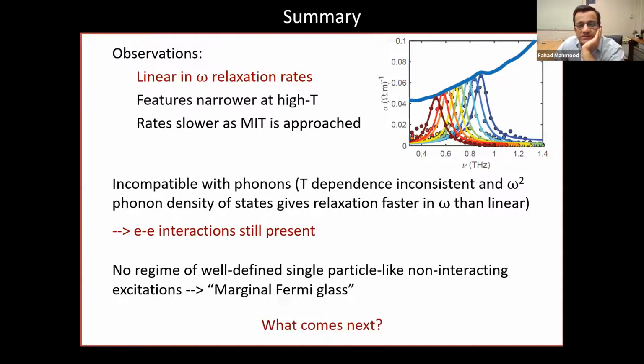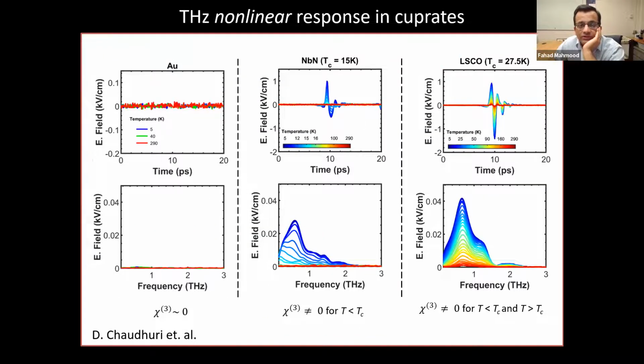As a follow-up to this, the student that I was working with, Dipanjan, has been working very hard to extend this to cuprate superconductors, and I thought I should flash these results because this is a workshop on unconventional superconductors. To highlight what we're measuring here, we essentially measure the third order susceptibility at terahertz frequencies. If you do this on a simple metal, gold, you essentially don't measure anything. It's very linear. There's very weak nonlinear susceptibilities. If you do this on a conventional s-wave superconductor, niobium nitride, you measure some nonlinear susceptibility, but that only onsets at the superconducting Tc, which makes sense because superconductors are highly nonlinear.